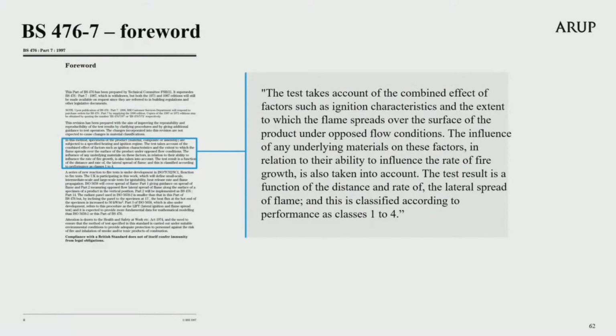There have been 3 versions of Part 7 published, first in 1971, with 2 further revisions in 1987 and 1997, and a change to the foreword only in 2014. The foreword section of Part 7 states, the test takes account of the combined effects of factors such as ignition characteristics and the extent to which the flame spreads over the surface of the product under opposed flow conditions. The influence of any underlying materials on these factors in relation to their ability to influence the rate of fire growth is also taken into account. The test result is a function of the distance and rate of the lateral spread of flame, and this is classified according to performance as classes 1 to 4.